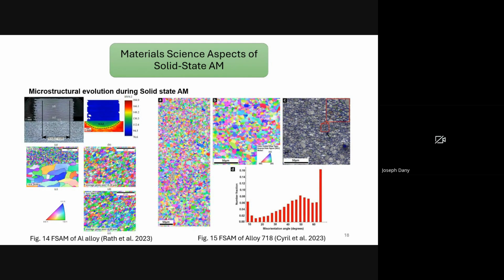Microstructural evolution in friction-based additive manufacturing is overwhelmingly governed by dynamic recrystallization (DRX), a direct consequence of the intense plastic shear and frictional heating imposed by the rotating tool. During the friction surfacing process, the material in the process zone is subjected to very large strain at elevated temperature, well below the melting point. Those conditions produce a very high dislocation density and promote recovery and rearrangement of dislocations into subgrain structure.